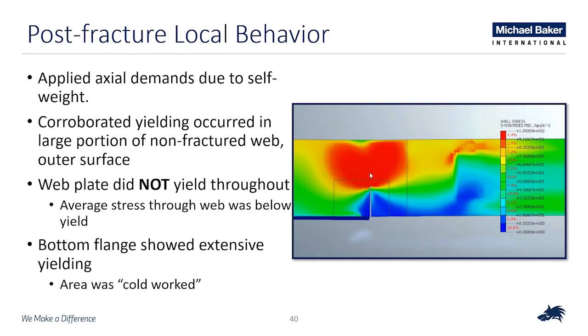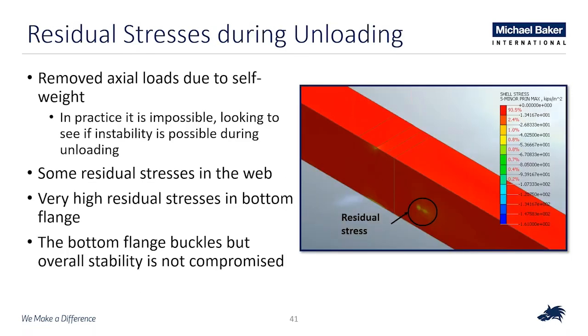The bottom flange picked up a very large amount of plastic deformation. It was almost as if the whole remaining ligament on the bottom cover plate had been cold worked; basically, plastic deformation was reached throughout that entire remaining ligament. If we go to the next one. So the first part was to see whether we had any additional capacity in that web plate, and it seems that although we were close to yielding, we still have some additional capacity in the remaining web plate. We weren't really that close to a full section rupture of the plate.